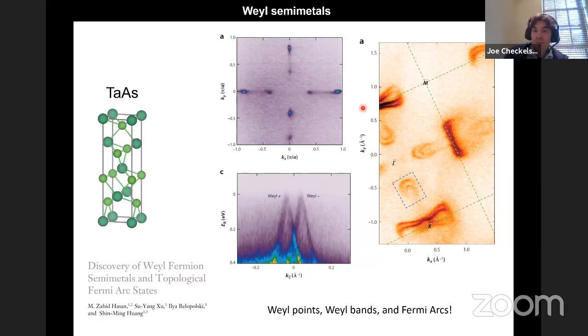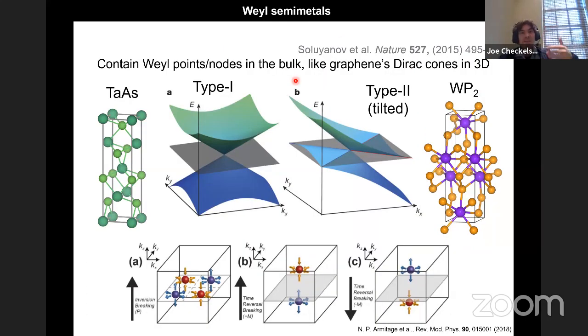And then when you go look at the surface, you can see these arcs, and these are Fermi arcs, which are basically on the surface connecting these Weyl points. So it was really just as was expected. And really, in the spirit of this field, it turns out there weren't just these types of Weyl systems. There are other types. There's type 1, there's type 2, which basically have different kinds of tilting of Weyl cones.